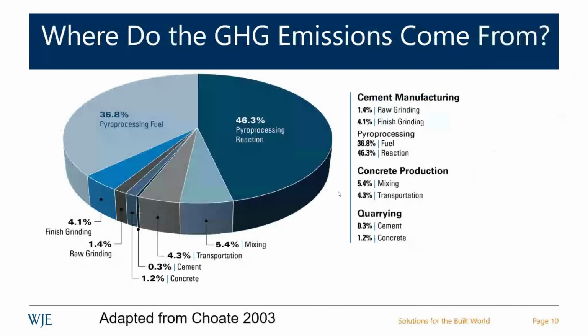So where do those carbon emissions come from? I think this has already been discussed in some detail, but the bottom line is if you look at this pie chart, and this is the emissions in concrete, 90%, 85% or so is basically from making clinker in the kiln. And then we've got the finish grinding. The raw grinding will also have some of that, a little bit of transportation. But when it comes right down to it, roughly 89, 90% is from the Portland cement.